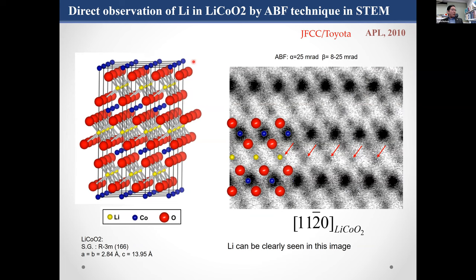We applied it to lithium cobalt oxide. This is the structure, and the large red circles correspond to oxygen columns and the yellow ones to lithium columns. We observed from this direction, the [1 1 -2 0] direction. This is the thus obtained ABF image. You can clearly see the lithium column contrast, indicated by these arrows. This is the first direct observation of lithium columns in lithium ion-related crystals.